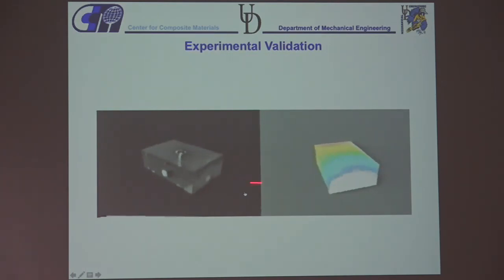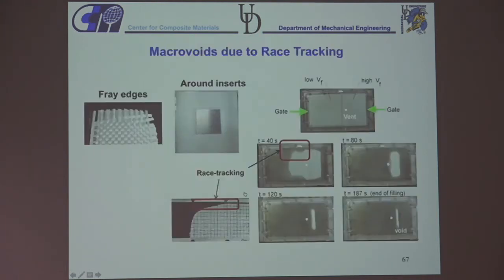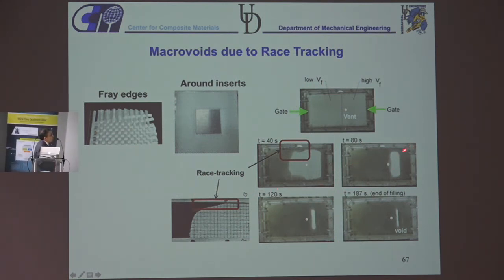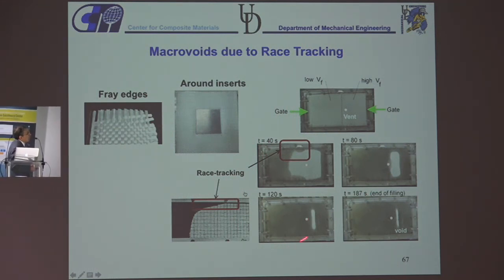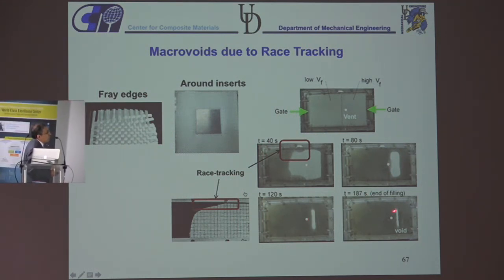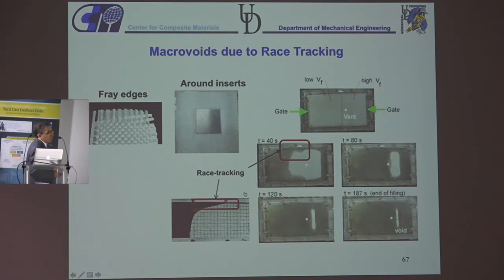And so simulation is on the right, and this is the experiment. And so many other examples of race tracking, like when you put inserts inside the mold, you can have race tracking. And what happens is when you have race tracking, if you don't include that in your simulation and you say, okay, the vent is here, then the flow goes faster there, goes past the vent, and even if you're letting the resin bleed, you have trapped this air and you can't get that air out, and you'll get a void there.